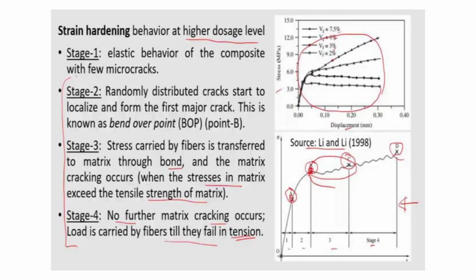Stage 1, elastic behavior of the composite, with few micro cracks. Stage 2, randomly distributed cracks start to localize and form the first major crack. This is known as the bend over point, BOP, denoted by point B. Stage 3, stress carried by fibers is transferred to the matrix through bond, and matrix cracking occurs when the stresses in the matrix exceed the tensile strength of the matrix. Stage 4, no further matrix cracking occurs. Load is carried by fibers till they fail in tension. That is how the stress strain curve behaves.